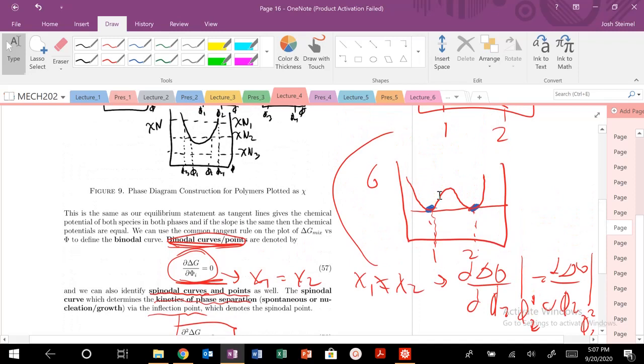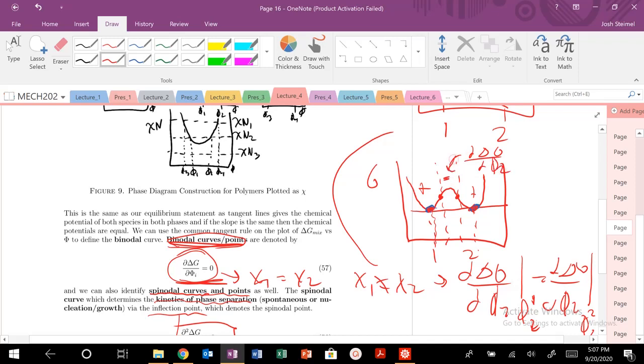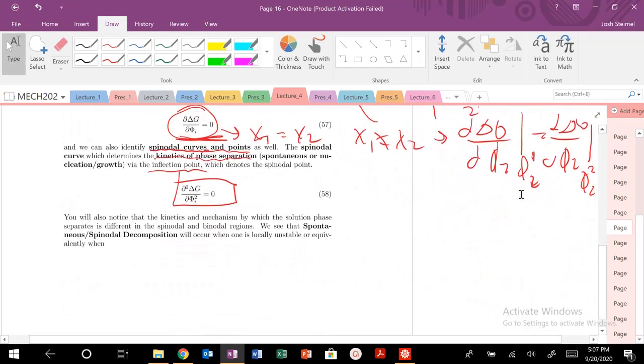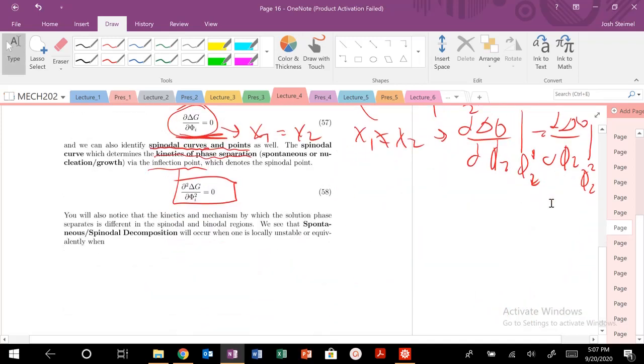I can always find my spinodal points mathematically. I know the change in inflection when I go from concave up on the outer sides to negative curvature in the middle region. In the spinodal region the second derivative of ΔG_mix with respect to φ₂ is less than zero — concave down. In the binodal regions, d²G/dφ₂² is greater than zero. These regions are really critical because they determine the kinetics of how we phase separate.